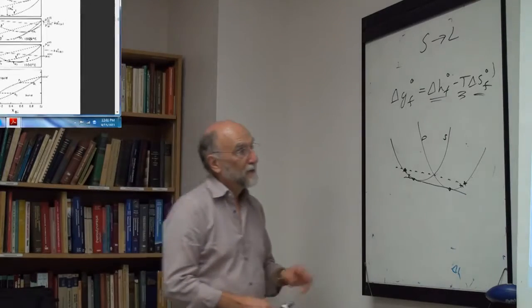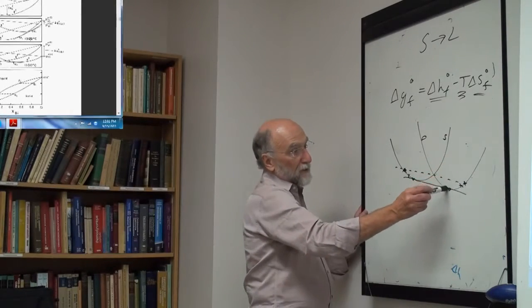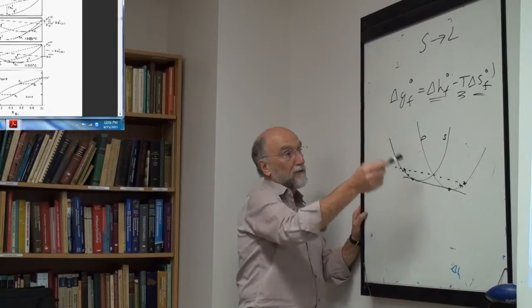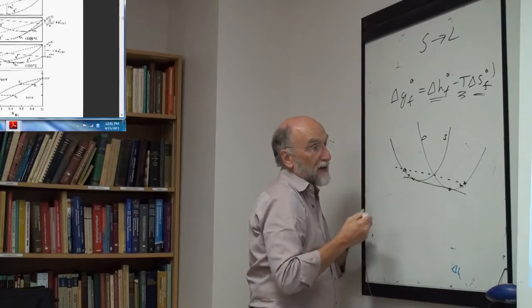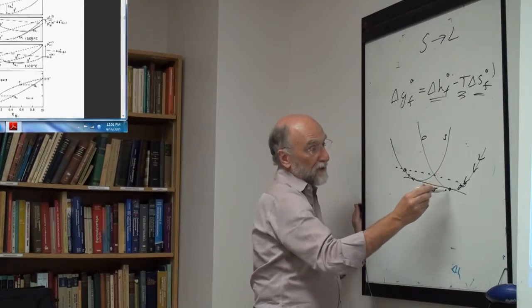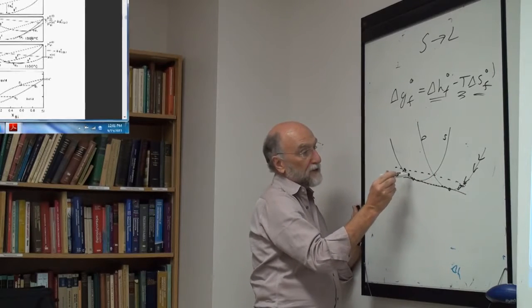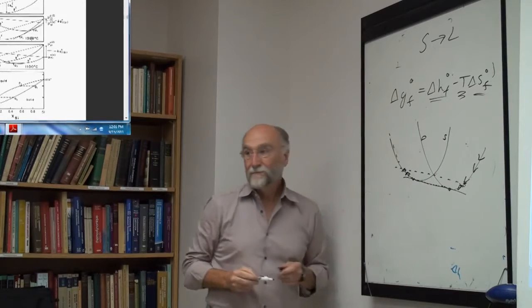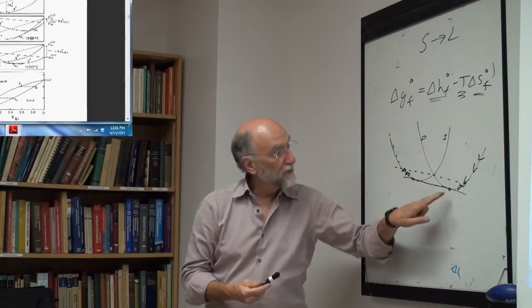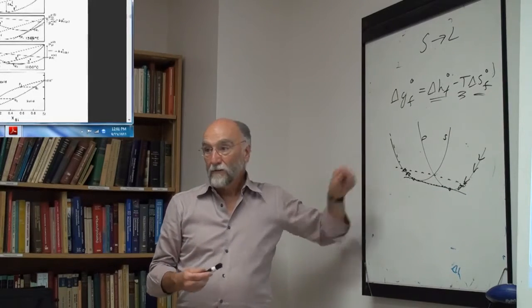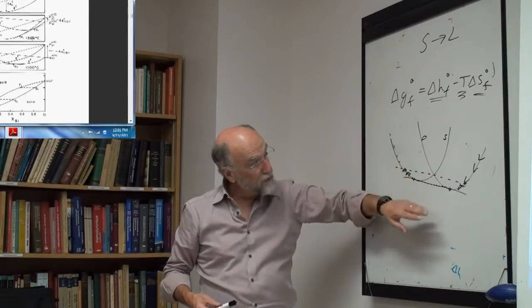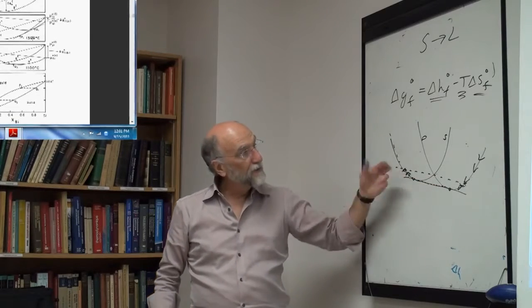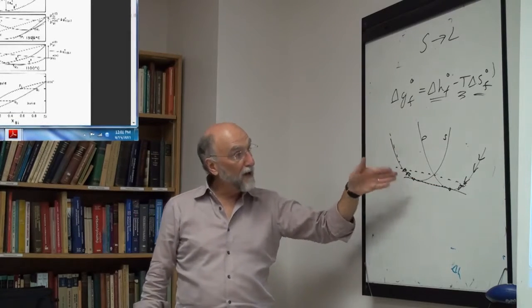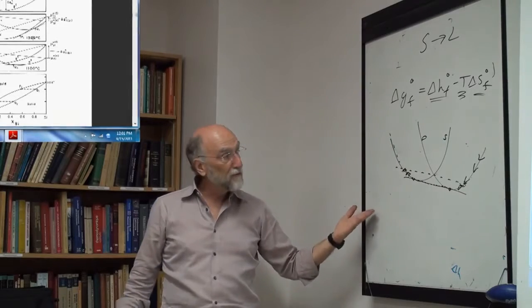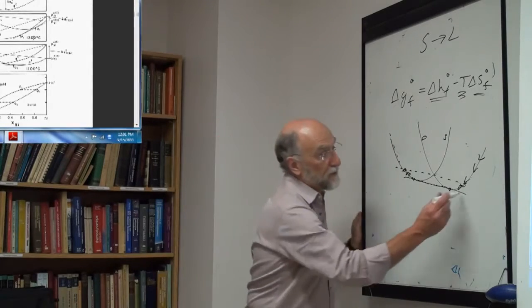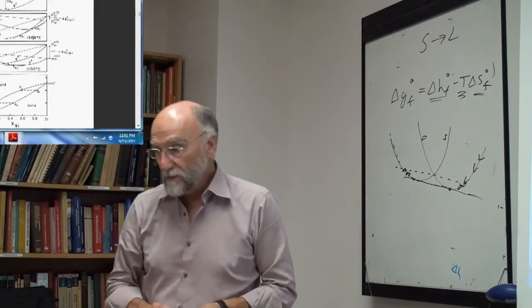It's the envelope. Over here you've got pure solid, you follow the envelope. Over here you've got pure liquid. So the actual system follows the one phase region here, moves along until it reaches here, and then goes up there. So you go through a one phase region, a two phase region. The common tangent is the lowest line joining a point on one curve to a point on the other curve, and it's also the line that gives you the same chemical potentials in the two phases.